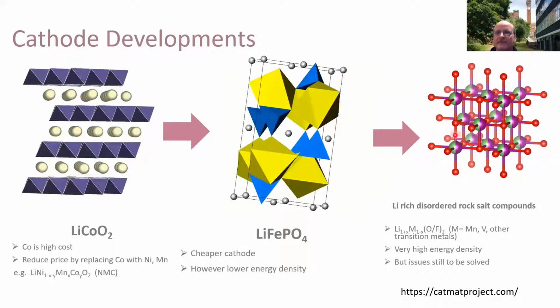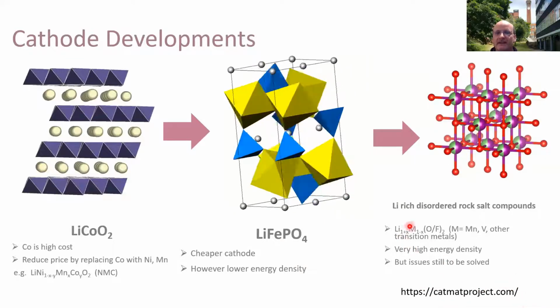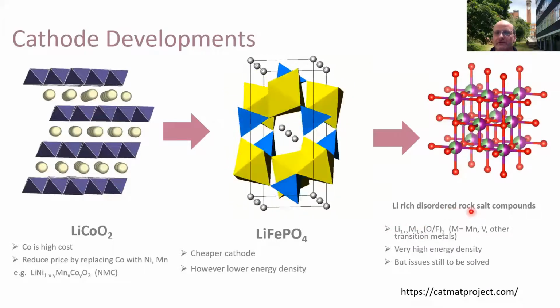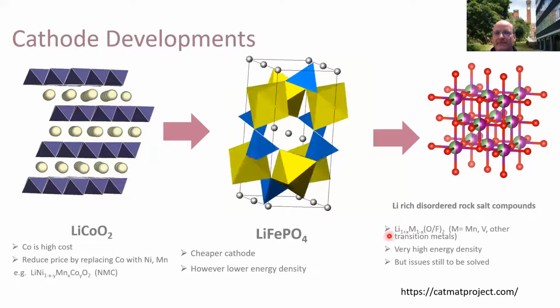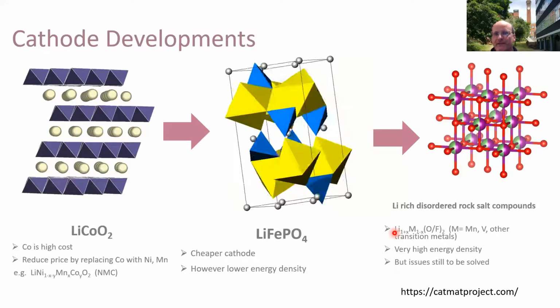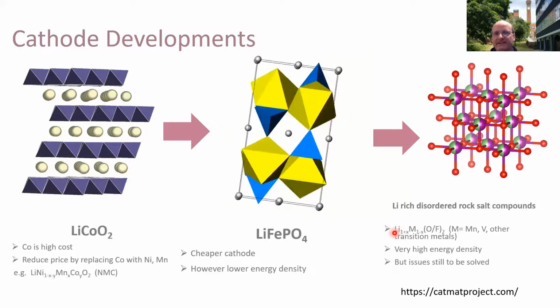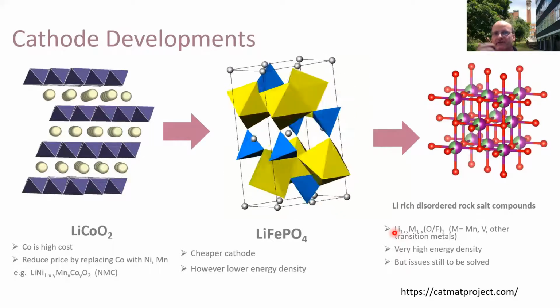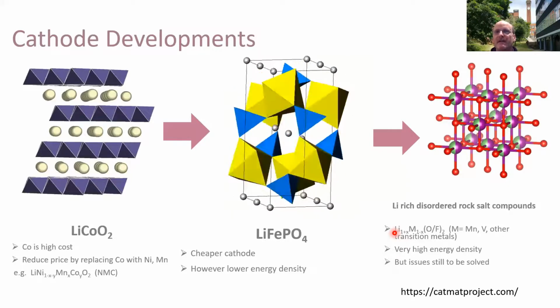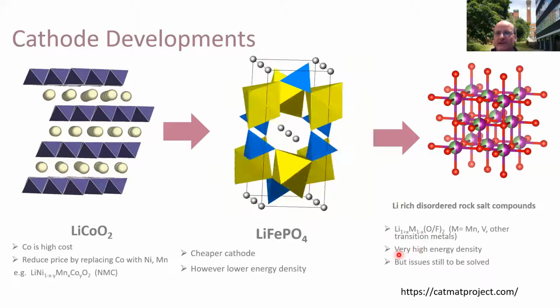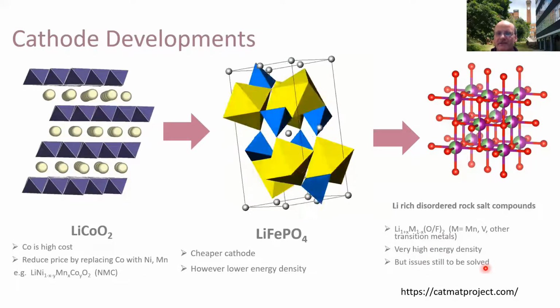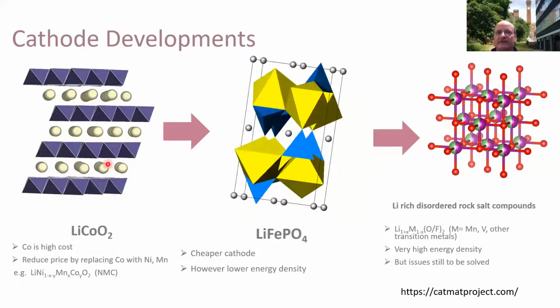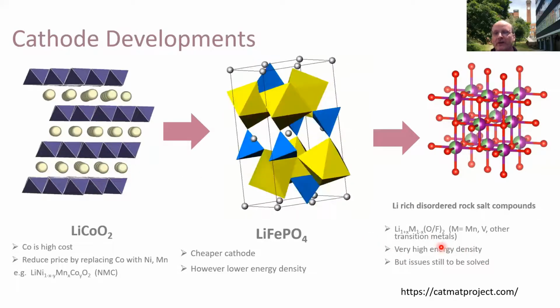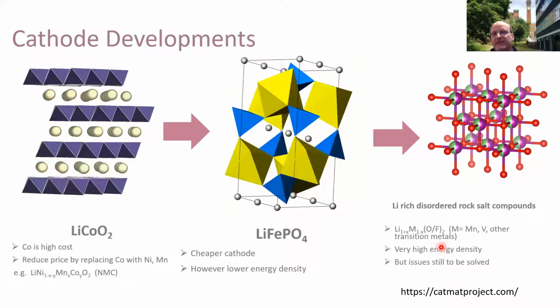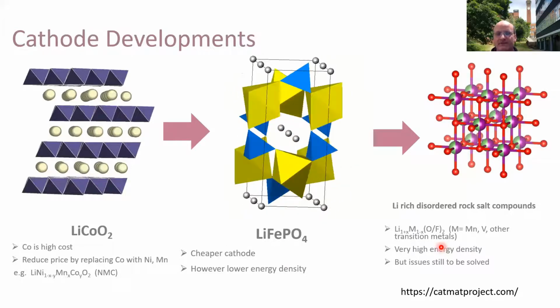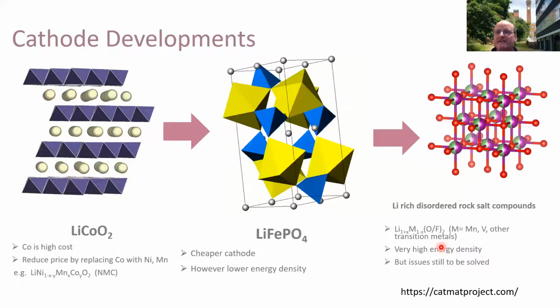And then the newer research, the sort of things that we're working on as part of the CatMat project, is these so-called lithium-rich disordered rock salt materials. The key thing with these is that instead of one lithium, we've got more than one. So we're increasing the amount of lithium in our material. Overall weight is fairly similar. And if we can increase that number of lithium and consequently remove more, our energy goes up. So in principle these give very high energy density, but at the moment there are issues to be solved. Their reversibility isn't as good at the moment as these other materials. So they give a much higher energy density to start with, but it rapidly fades. So it's trying to understand why it's fading, what the degradation routes are, and trying to develop ways of overcoming these.